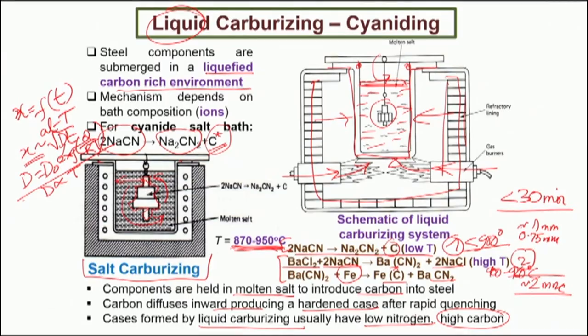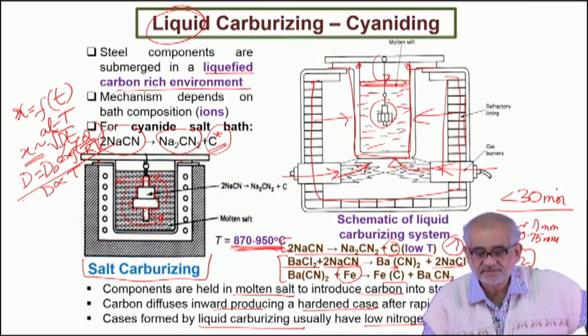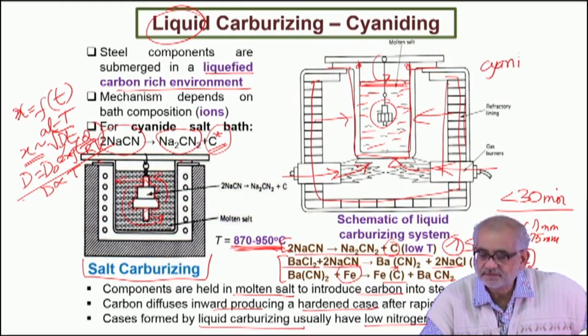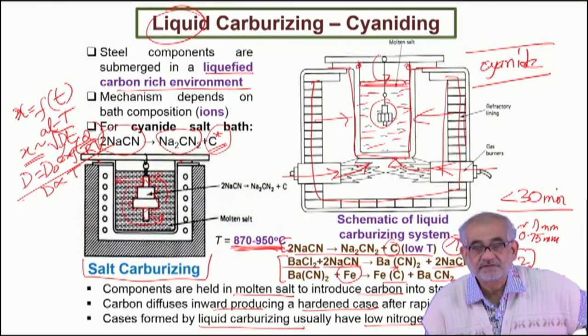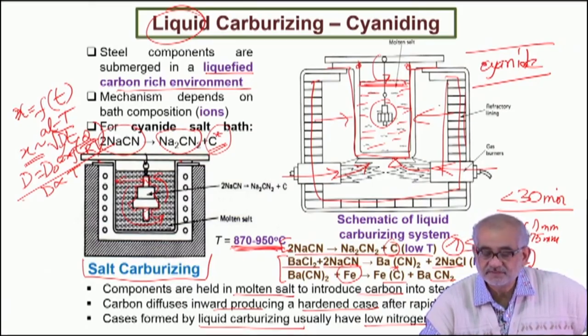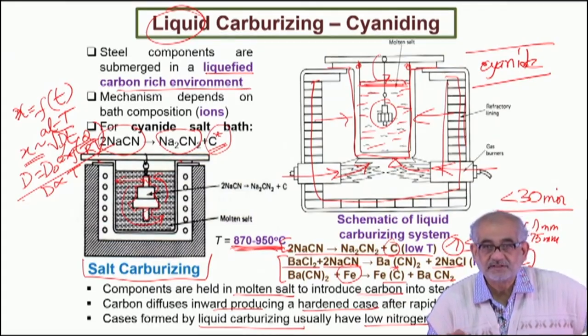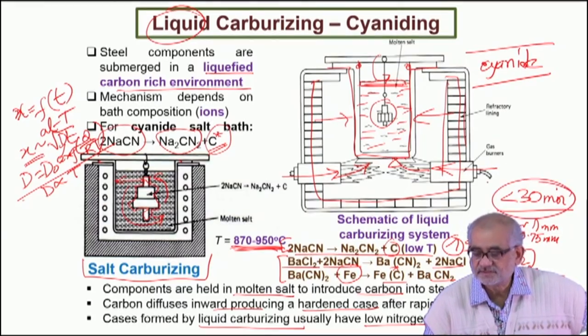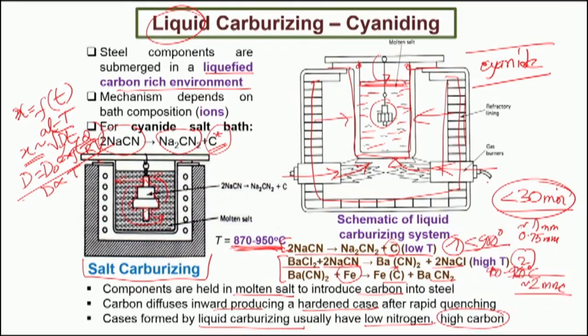The introduction of nitrogen increases surface hardness even further, which is both good and bad. The good news is higher hardness and better wear resistance; however, if the surface is made too hard there is no scope for further machining or shaping as a follow-up. The biggest disadvantage of liquid carburizing is the use of cyanide — an extremely toxic compound. Accidentally inhaling cyanide vapour can cause very lethal effects, so disposal and recharging of the molten salt are fairly hazardous processes. Despite being kinetically rapid, liquid carburizing or cyaniding is not widely adopted in industry.